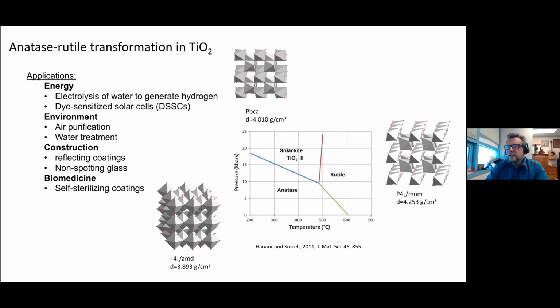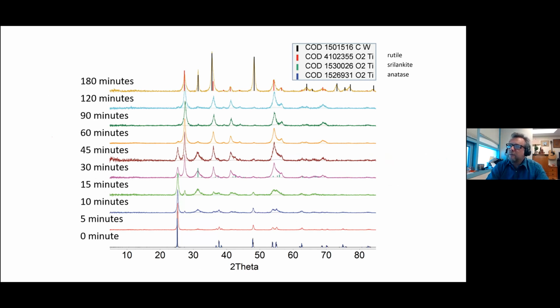The second project we decided to undertake to understand the utility of high energy milling for inducing phase changes was titanium oxide. In this system, we were interested in 3 different polymorphs, anatase, srilankite, and rutile, which have different densities. We thought that looking at kinetics, at the evolution of phase fraction of the 3 phases as a function of the time of milling, would be quite interesting. So again, we started with a sample that contained only anatase phase. We performed a milling experiment under similar conditions using the same type of jars and about 3 hours of milling time.